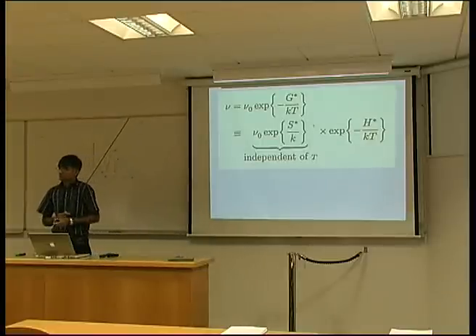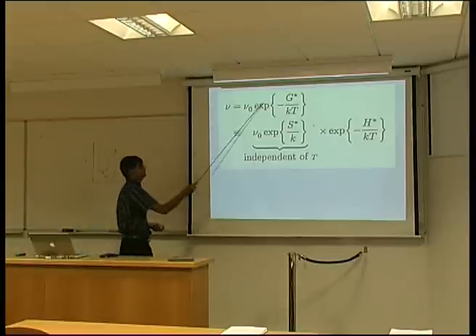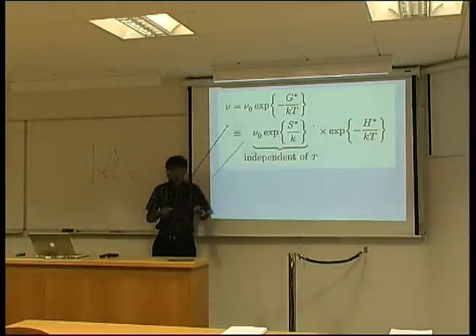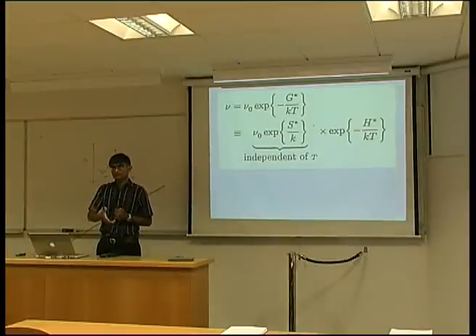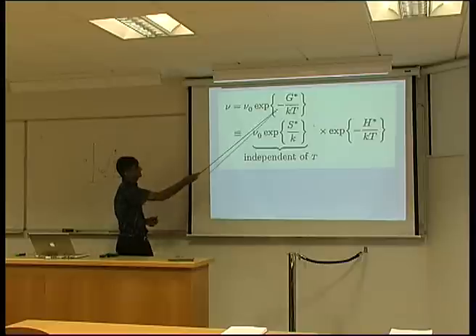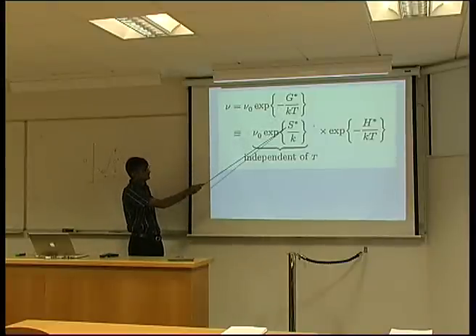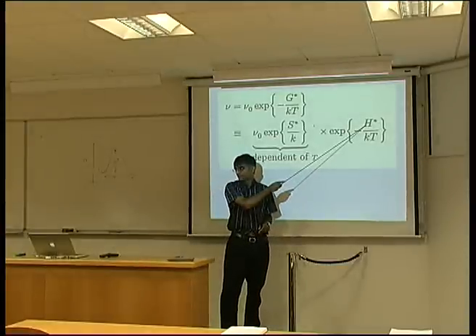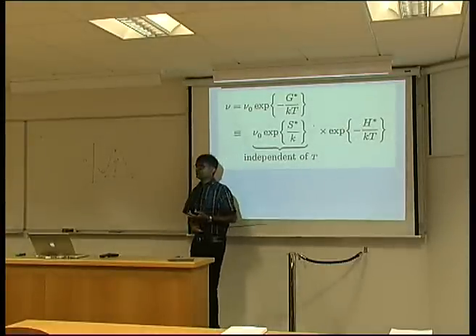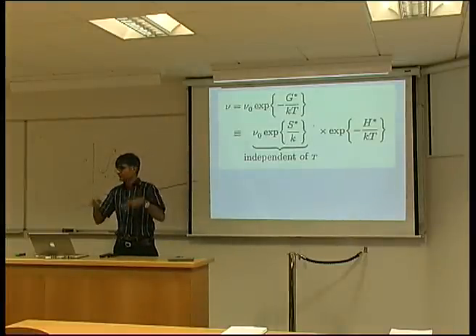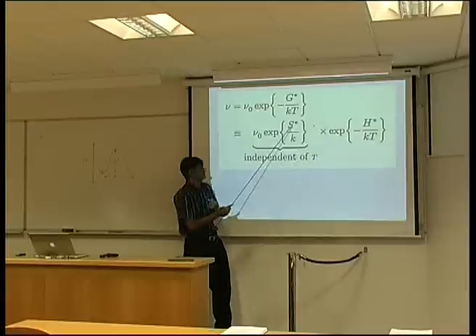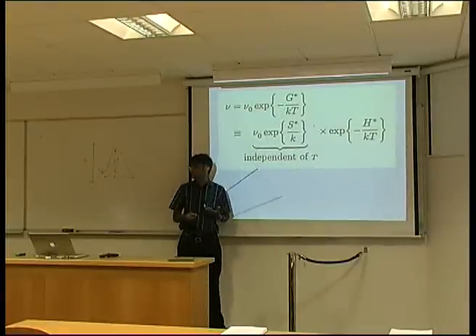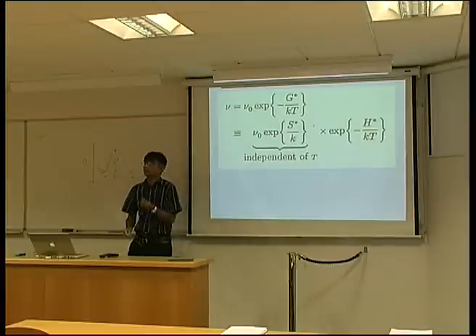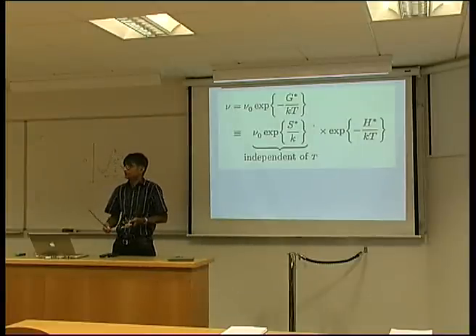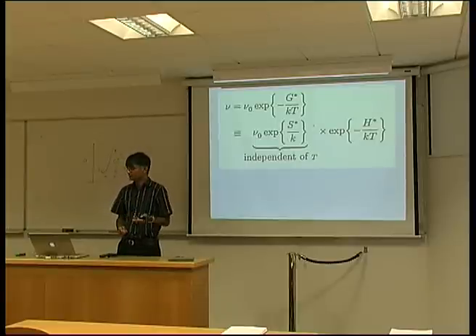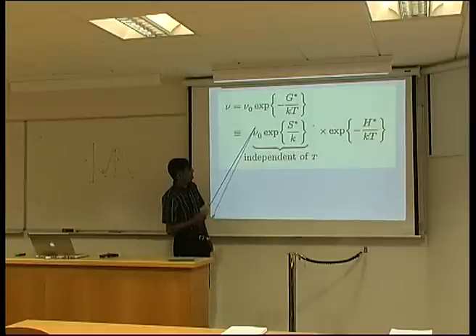So obviously at low temperatures this becomes very difficult, because this exponential term will be very small when T is small. That makes sense, because diffusion at low temperature is more difficult than diffusion at high temperature. And I can expand this activation free energy into an activation entropy and an activation enthalpy. And in the textbooks, sometimes they don't explain what they mean by activation energy. This is an enthalpy. This is an entropy and this is a free energy. You should really think in terms of just those three quantities rather than using general terms like energy. Energy could be anything. It could be enthalpy, it could be Gibbs free energy, it could be Helmholtz free energy, and so forth. Now, obviously this term is independent of temperature.